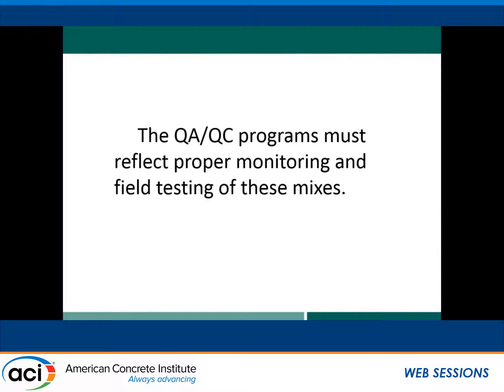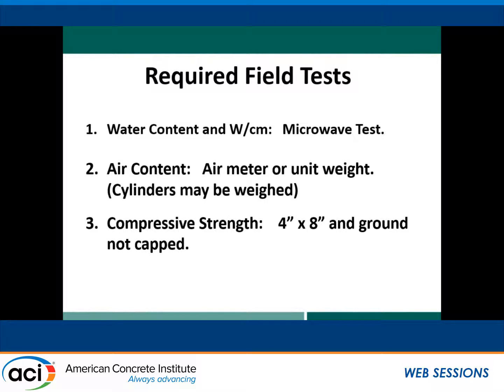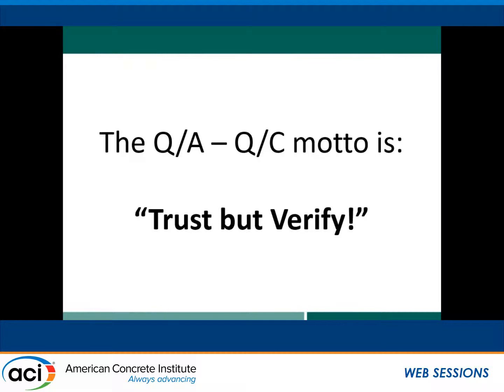QAQC requirements are very important to reflect proper monitoring and field testing. Water content is controlled via microwave testing. Unit weight is monitored to verify air entrainment levels. For compressive strength testing of high-performance concrete, capping is not acceptable — cylinders must be ground. Make sure the selected lab is familiar with testing high-performance concrete. Monthly charts may be required for water-to-cement ratio, compressive strength, and slump flow range. The QA/QC motto is: trust, but verify — enforced through rigorous quality control, especially the microwave test.